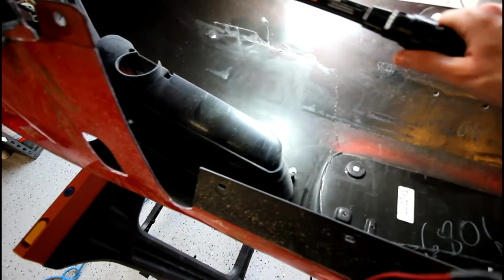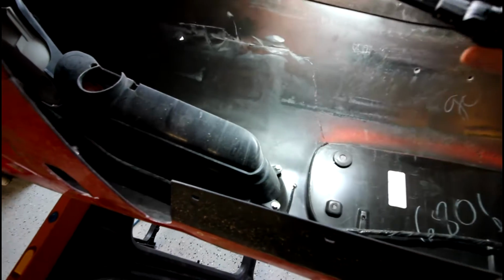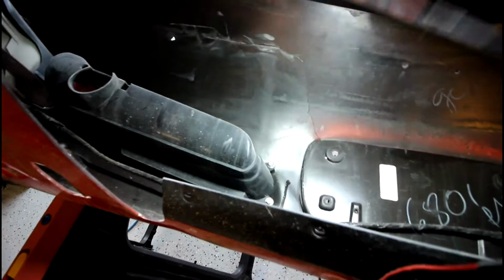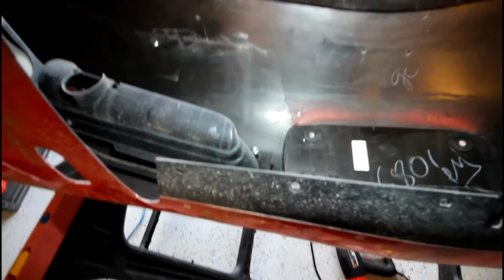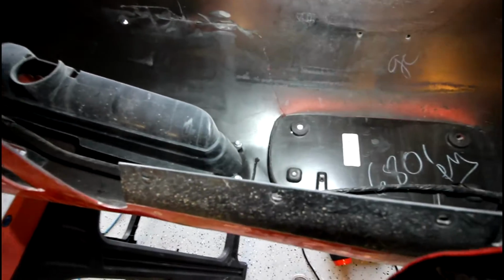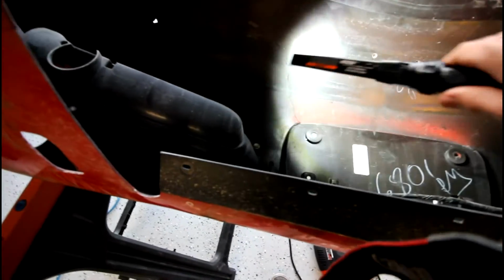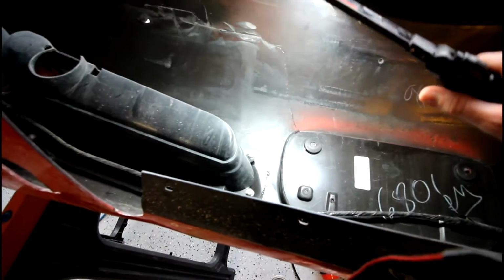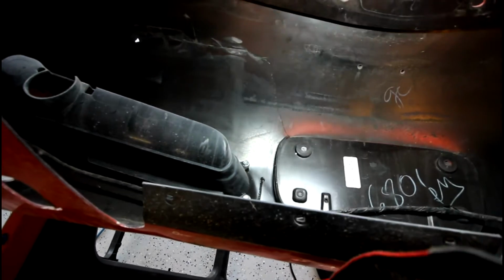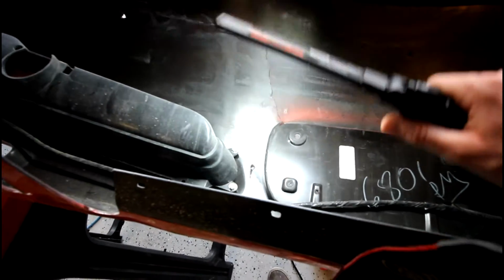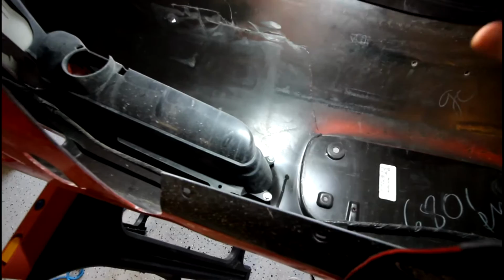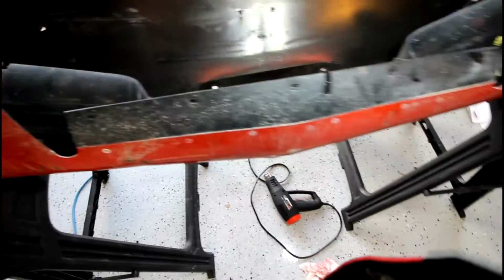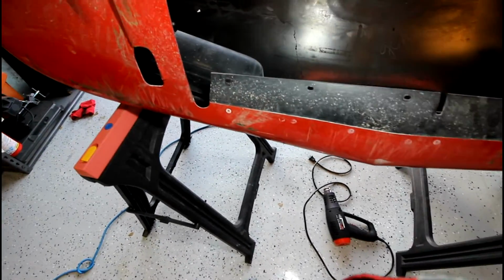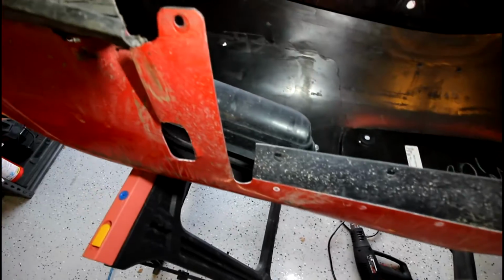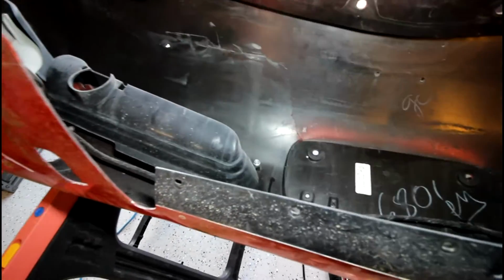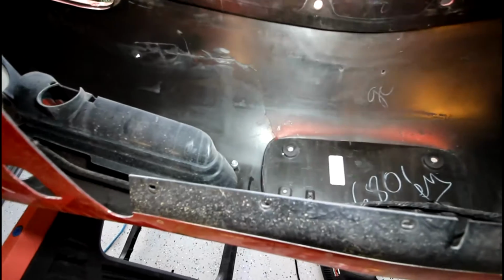So you want to go along the length of the crack, follow it, and use your angle grinder to give it a groove. And that, in a sense, gives you better weld penetration. Like with conventional welding, you want to grind out that groove so that the weld goes deeper into the plastic and it's not just a surface weld, because that'll definitely crack when this thing flexes, because these polyurethane bumpers are made to flex a little bit and expand and contract with hot and cold temperatures. You want a strong weld or else the crack's just going to happen again.